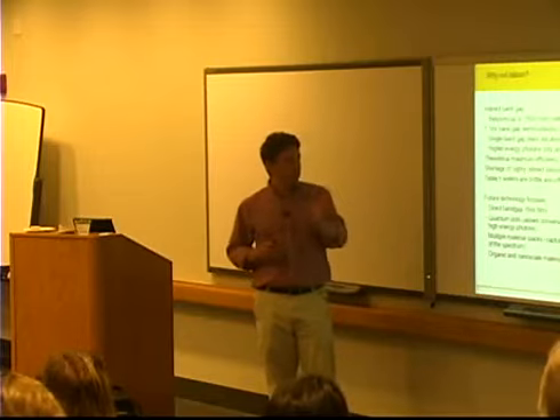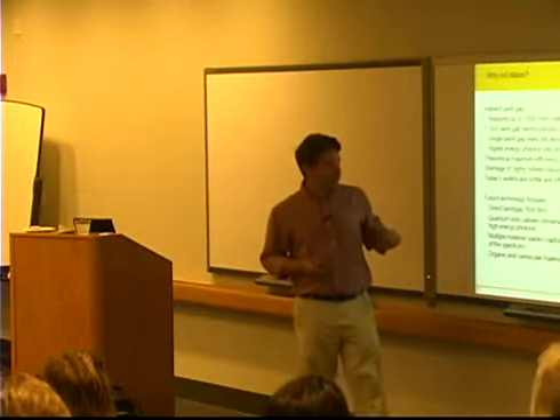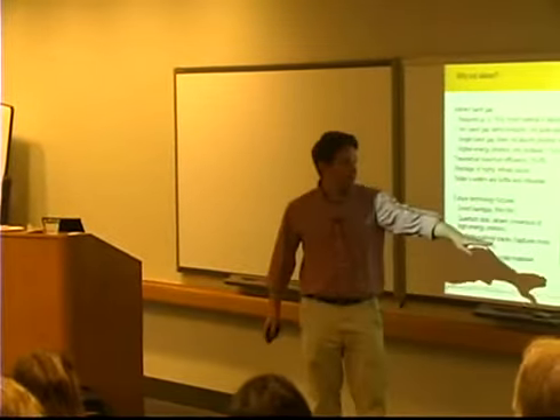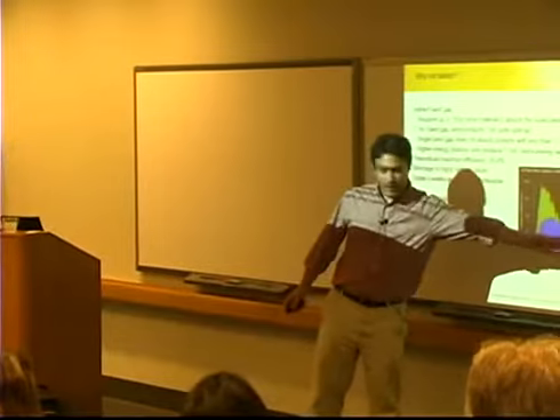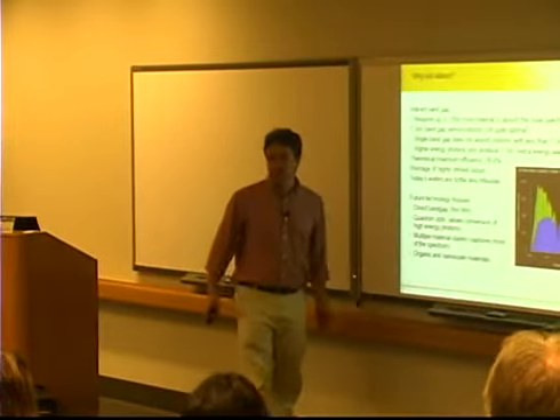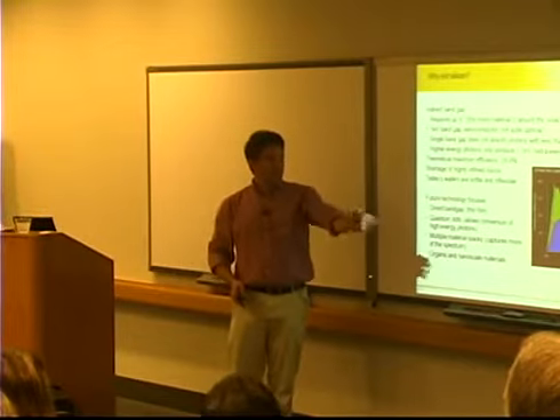A single band gap of course does not absorb photons that are less than 1.1 eV. So we are, in fact, cutting out the infrared part of the spectrum. And this is a full 30% of the solar energy that we're more or less throwing away by drawing our single band gap cutoff line here.